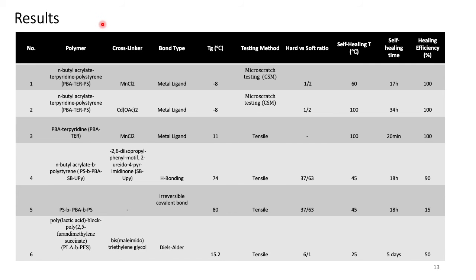Here are the main results that were obtained, which show the polymer and also the parameters that affect the self-healing and the self-healing efficiency. Of course, we cannot compare all of these because of different testing methods for each one. However, we can, for example, compare these two, in which they use the same material, almost the same conditions, however, a different cross-linker, which shows that manganese chloride gives better self-healing efficiency because it requires less time and also a lower self-healing temperature to reach 100% efficiency in comparison to the other cross-linker.